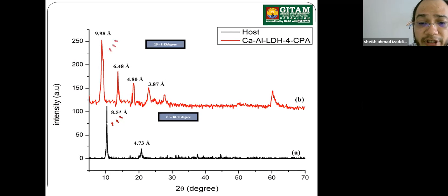Okay, and then for the calcium aluminum 4-CPA, which is represented by the red line, it's synthesized through the co-precipitation method. It displays a slight shift downward from 2 theta 10.35 degrees to 8.85 degrees, which represents a sharp, highly crystalline and symmetric peak with a basal spacing of 9.98 Angstrom, which represents the wider basal spacing after the integration process took place.